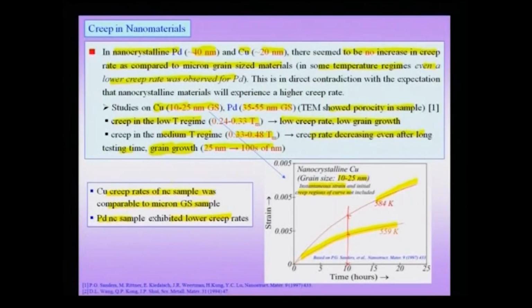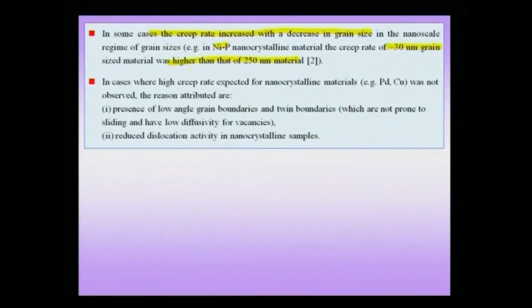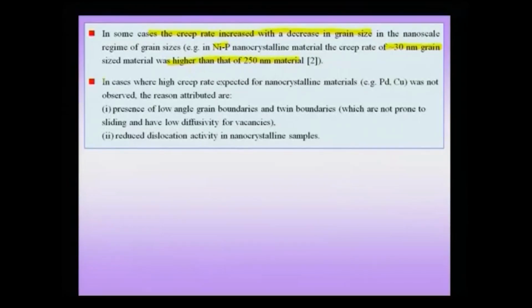Of course, the comparisons are slightly different, because in the first case, in the case of copper, we had compared the nano grain size with a micron grain size sample. Here we are comparing two nanometer grain size samples, and we see that there is actually an increase in creep rate as we decrease the grain size. In cases where high creep rate was expected for nanocrystalline materials, like we see for palladium and copper, which are nice metallic materials where the diffusion rate is high, it was not observed.